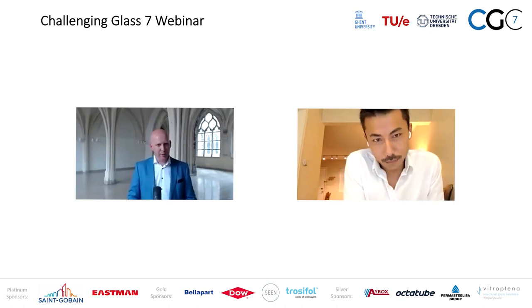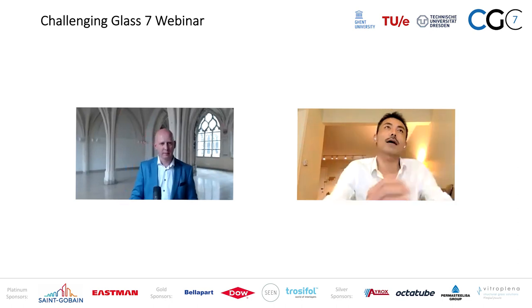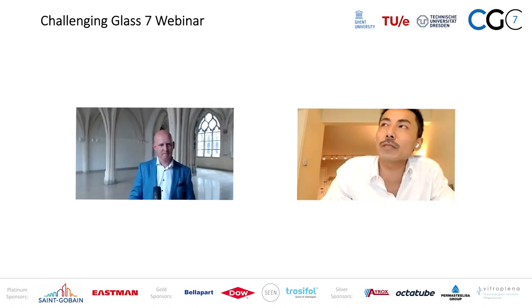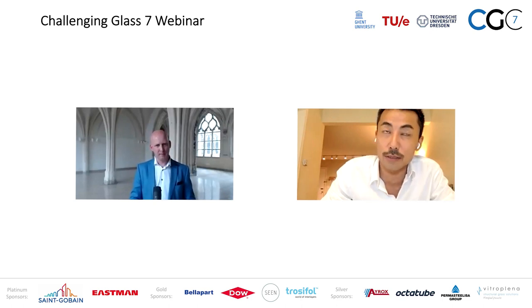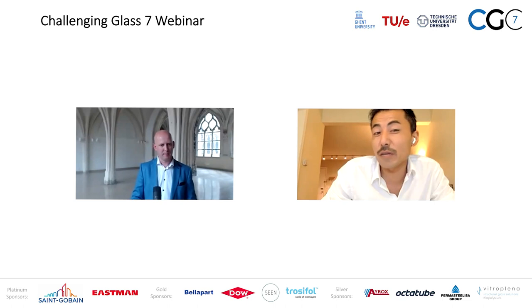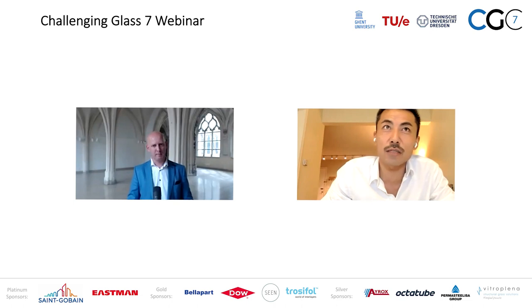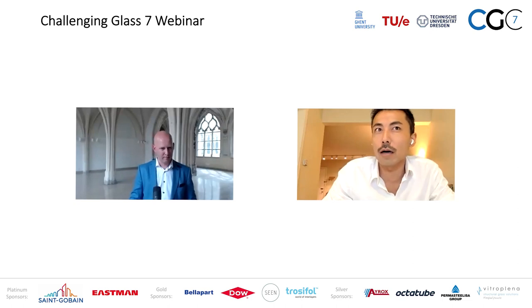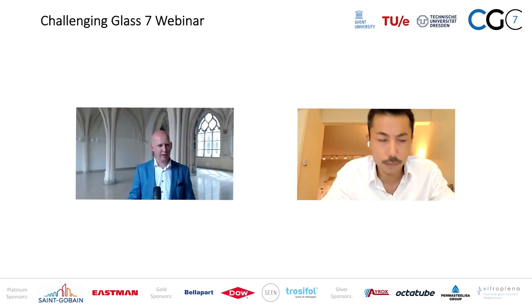Peter Lenk asked about how do you maintain the dimensional stability during the printing? And what is then the tolerance of the product in the end? That's a good question. Overall, we achieved within 10% of a dimensional accuracy from input design. The nominal cross section is about 10 to 12 millimeter, and the thermal accounts for about 0.5 millimeter, and the motion accounts for additional 0.5 millimeter. So in total, plus minus 1 millimeter. Okay, that's relatively accurate.